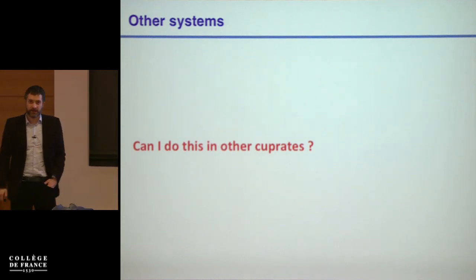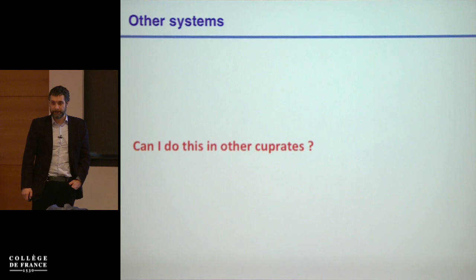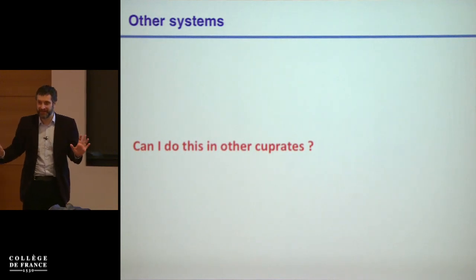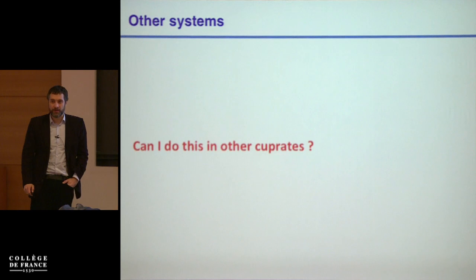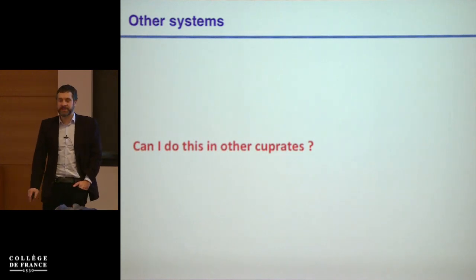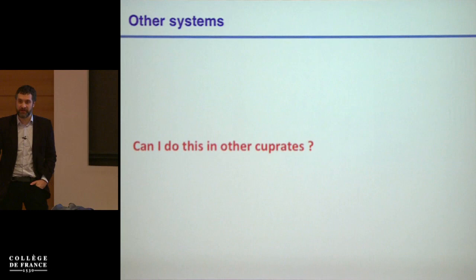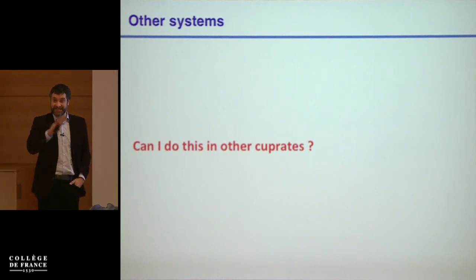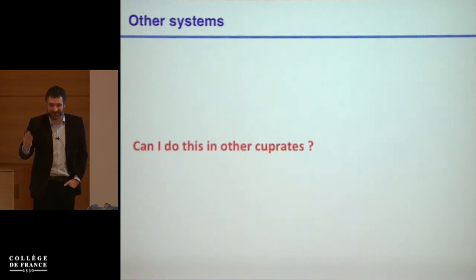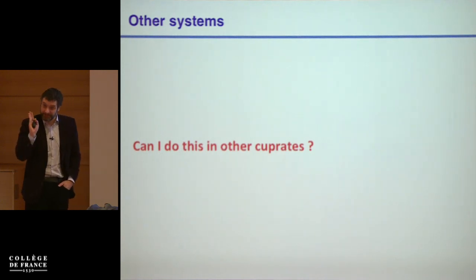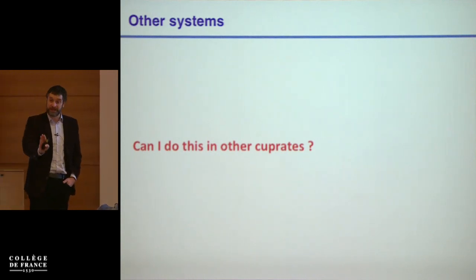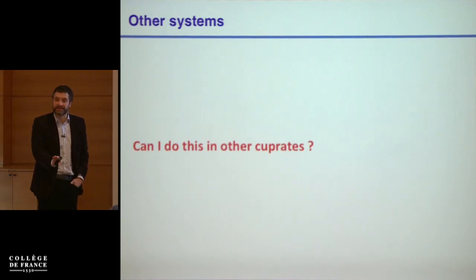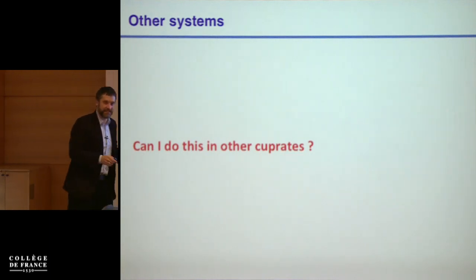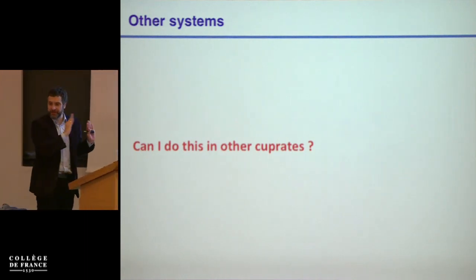It might be that you are seeing fluctuating pairs, but not the real superconducting state. Yeah, absolutely. Any of the above. So you will detect if there are fluctuating pairs forming. That's not something I'm saying. Okay, let me just be very careful. What I'm saying is that if I take a system that is not superconducting and I drive the phonon, I observe signatures of superconductivity, and up to now, so we can get to fluctuating pairs in about 10 minutes, up to now, we have told you that this happens when static charge order is being melted. This is what the 1/8 experiments tell me.